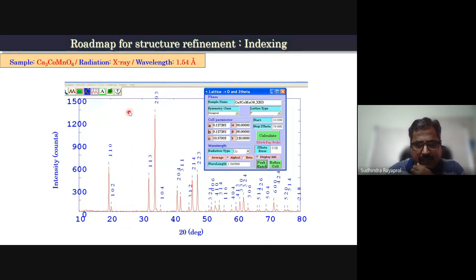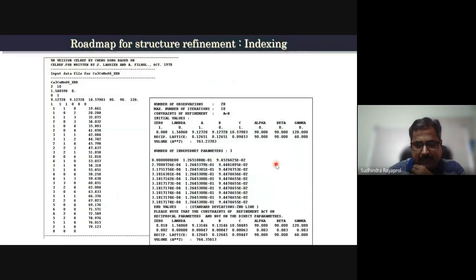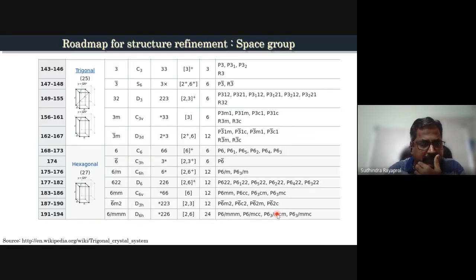Once you have identified all the Bragg peaks, you can do the refinement. So this is the information you get. This is your starting values of ABC values, and this is the refined cell parameters. So now what you have is HKLD values and refined cell parameters. Once you have the cell parameters, you know what type of crystal system it is. You have indexed the pattern.